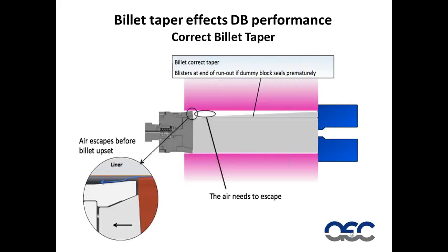I talked quickly about rate of expansion of the dummy block. The other half of rate of expansion is what the billet actually looks like. If we take a thermal profile of the billet, we would hope that the back of the billet was colder than the front of the billet. As we know from many of the talks we've had before, flow stress is increased when the billet becomes cooler. So if we have a billet that's tapered so it's hotter at the die end than the dummy block end, we can get a consistent or a progressive rate of upset, in which case the air is pushed to the back where the dummy block is, and the dummy block then, if it's working correctly, will enable us to evacuate the air.